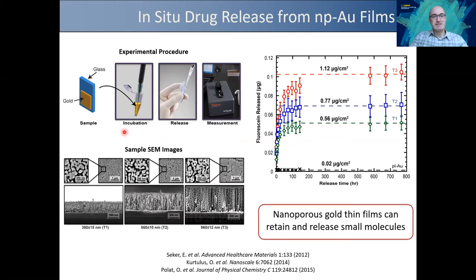Basically, it started with a simple study. You have samples with a gold or a nanoporous gold pattern on them with various thicknesses. We incubate them in fluorescein in deionized water, which is a good small molecule drug surrogate, and it's easy to quantify because of its fluorescence. You rinse it and then put the sample in another PCR tube with deionized water, sample the release over time, and quantify it with NanoDrop fluorospectrometry. What you see here is the release time and the fluorescein release. As you increase the thickness, the loading capacity increases.